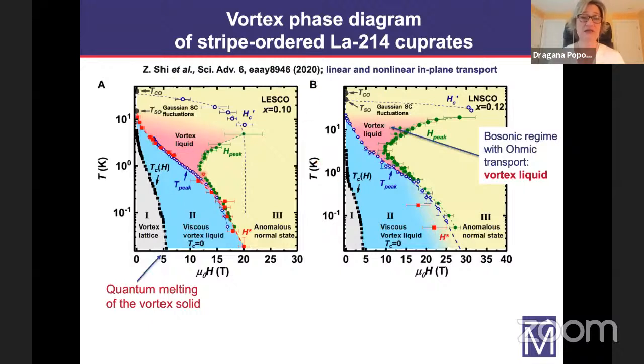So in addition, at these high temperatures in this regime here, we have ohmic transport, but this is a bosonic regime. We have positive magnetoresistance. So we identify this as the vortex liquid. So basically, what this phase diagram is telling us is essentially what you would expect. At high enough temperatures, thermal fluctuations melt the vortex solid into vortex liquid. As you reduce the temperature, thermal fluctuations become less relevant. Vortices start to feel the effects of disorder, their motion slows down, and the resistivity drops, eventually goes to zero, and it freezes into vortex glass at zero temperature.